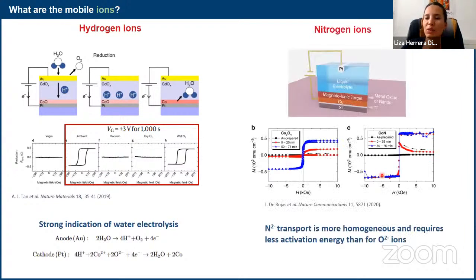And then recently, the group in Barcelona, who work more in this electrochemical approach that I was talking about before, could show the conversion between cobalt oxide and pure cobalt with the associated changes from paramagnetic to ferromagnetic. But they could do it as well with cobalt nitride. Here, the difference is that the transport of ions is based on nitrogen diffusion. And they could show that the nitrogen transport seems to be more homogeneous and that it requires less activation energy than for oxygen. So it seems that there is really also a lot to be done in terms of what ions are used for this. So we're not limited to just oxygen.